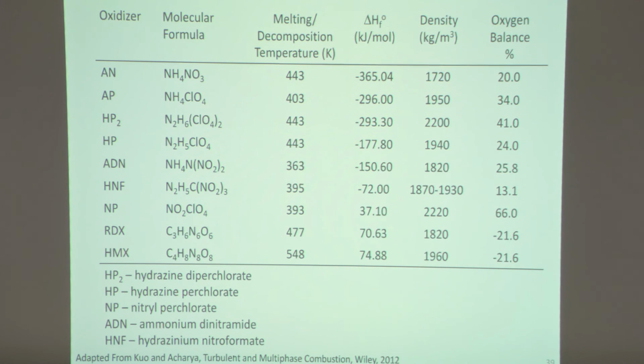So having a lot of oxidizer is going to be important to get the right equivalence ratio, but also increasing the density of the initial material. And you can see the oxygen balance. If I look at all the ones at the top, I'm going to be supplying oxygen to the formulation, and the 2 at the bottom, which are the high explosives, RDX and HMX, have a negative balance. And as I said, they're balanced almost perfectly for a solid propellant because they form CO, H2O, and nitrogen.